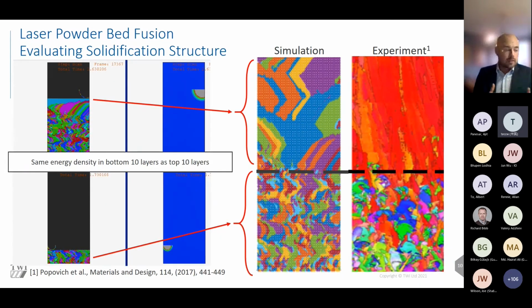But it's not just phases, alpha and beta and martensite, that influence properties, but also the solidification microstructure. And that's really important. As this cools from liquid, we will get nucleation in the melt pool and on the boundary of the melt pool. And then those grains will grow, and they'll grow dependent on the melt pool size and the thermal gradient.